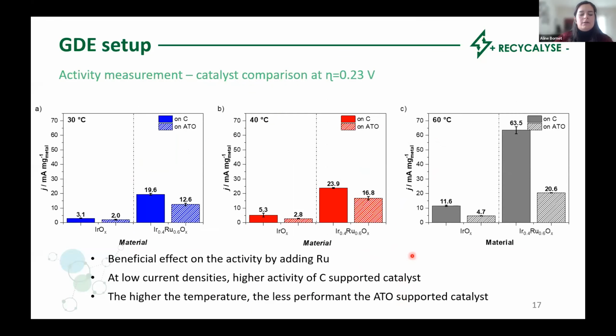We did the exact same current stepping experiment for each catalyst, and we compare them on those bar diagrams where the current density at an overpotential of 230 millivolt is plotted. This overpotential was chosen as it lies in the linear Tafel region of all individual catalysts at most temperatures. The full bars correspond to the nanoparticles deposited on carbon and the dashed ones on ATO. And on the left-hand side of each graph, it corresponds to the iridium nanoparticles, and the right-hand side, it's the iridium-ruthenium nanoparticles.